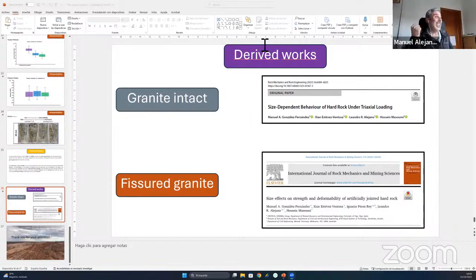There are areas for improvement. For example, in the process of making the sample preparation, because you have to be very careful. I can tell you that, for example, for the 38 millimeter diameter, we performed 25 tests, but I prepared nearly 60 samples that were not usable. So I prepared in total 90 samples.